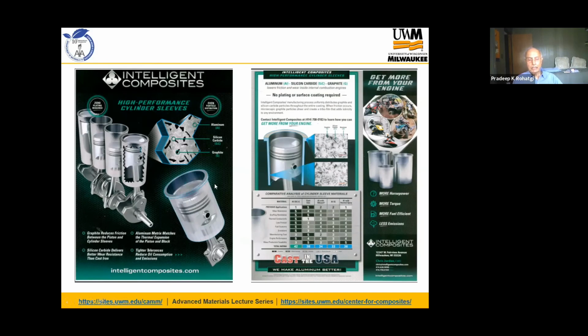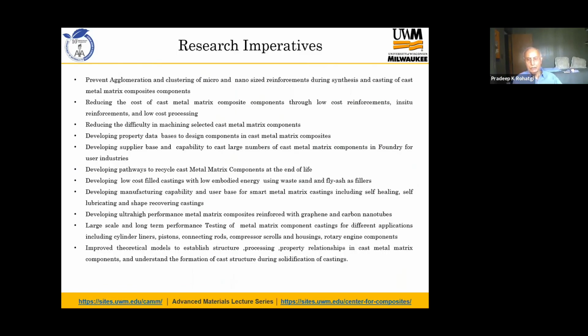This has been successfully cast as cylinder liners, and this table shows how the properties, the strength and thermal conductivity of this hybrid metal composite are better than cast iron, aluminum silicon alloys, nickel coated aluminum alloys, and so on. And these liners, Intelligent Composites has tested in small engines, in watercraft engines, in motorcycle engines, and hopefully they will be used in automotive engines to reduce energy consumption.